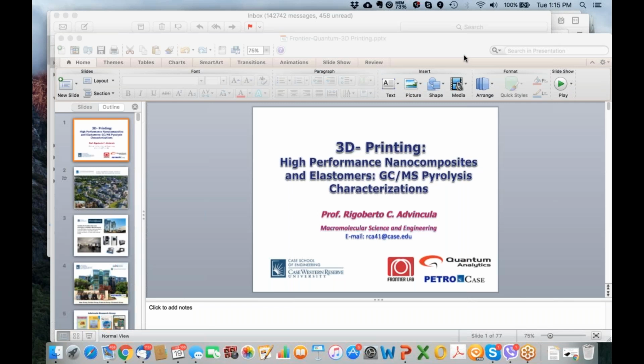Well, the primary difference to look at first would be the design and the mode of pyrolysis. So the frontier pyrolyzer uses something called the vertical drop microfurnace. It can be best thought of as a furnace region that's preheated to a temperature of interest, say 600 degrees C. And the initiation of the analysis comes about when you then drop the cup with the sample by gravity into the preheated furnace. So the placement of the sample, the introduction of the sample, and the temperature that the sample sees are all very reproducible, and that's what results in the high precision and the very good reproducibility from sample to sample.